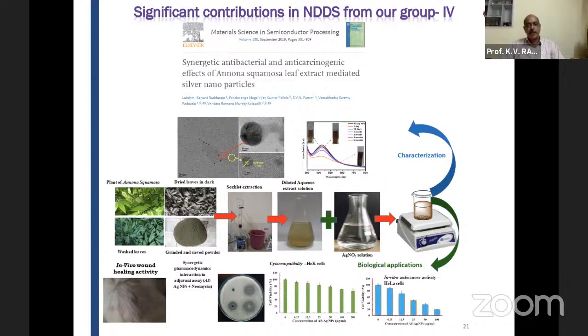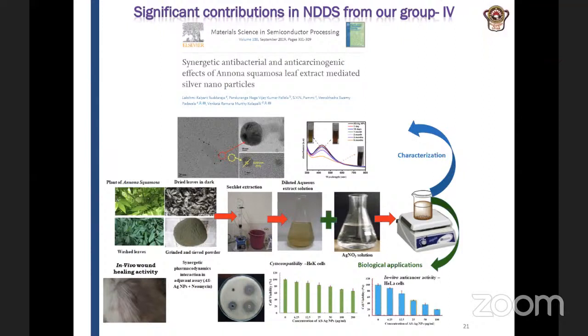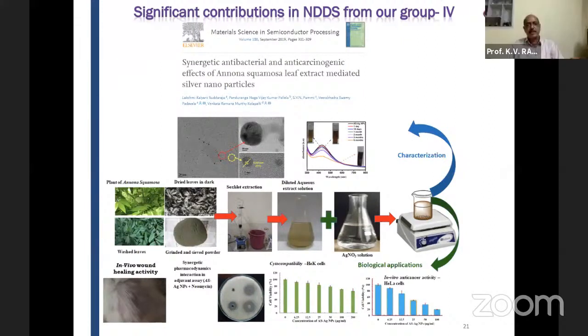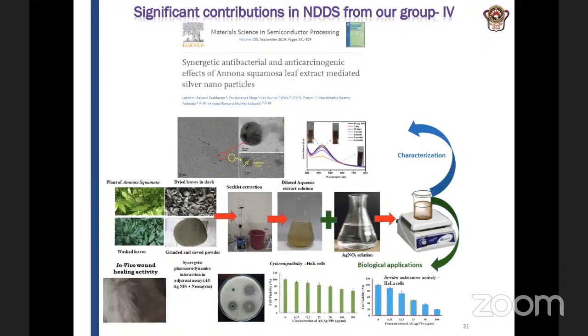So we prepared Annona squamosa leaf extracts of different kinds, and finally we optimized all these extracts, and we found that phenols are more concentrated in the aqueous extract, approximately 150 micrograms per ml of phenol content, which is the highest. We contemplated that this can be used as a reducing agent for preparation of the metallic nanoparticles. So we tried to prepare silver, zinc, and copper metallic nanoparticles using this Annona squamosa leaf extract, and we were able to synthesize and characterize these three different metallic nanoparticles, and we evaluated them for various applications.